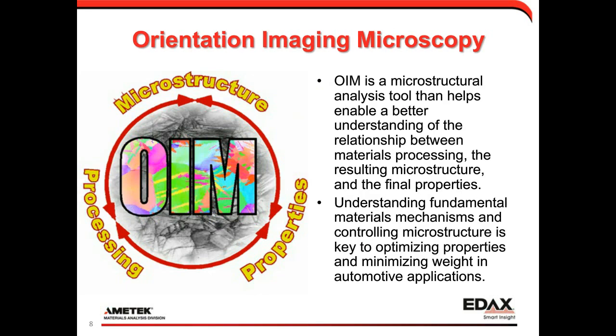So the approach that I'm going to talk to you about today is what we call OIM, or Orientation Imaging Microscopy, which really falls into that classical material science idea of your materials processing will define your microstructure, which defines your properties. As you adjust your processing to get different properties, you're essentially altering the microstructure. And so by being able to better characterize the microstructure, you get a better understanding of the relationship between the processing and the final properties via the microstructural constituent measurements. As you push to minimize weight and optimize properties, you want to know, if I go to a higher temperature, if I cool at a faster rate, what is that actually doing? Because then you can come to a more fundamental understanding of saying, if I want this property, I really want this microstructure, how do I get it?